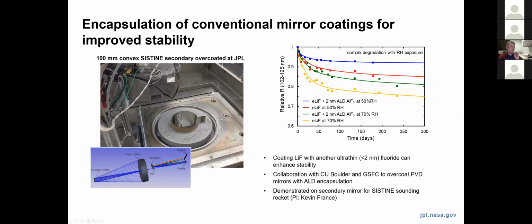Here's just some of the results of some aging studies that we've done with CU Boulder for this encapsulation process, showing the effect of long-term storage at elevated relative humidity levels over time for different RH conditions. And we saw that although these thin ALD layers could not completely eliminate the degradation, they could measurably slow it down. And so we've demonstrated this process initially on some optics that were flown in a sounding rocket payload called CHESS out of CU Boulder. And we're planning, as I mentioned, to do the same thing for this SPRITE CubeSat.